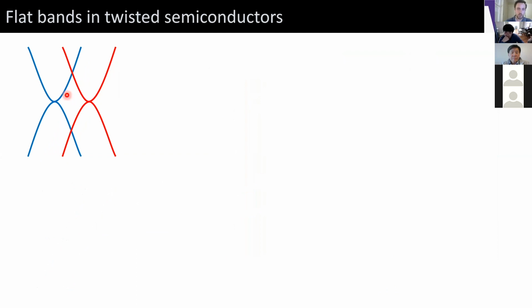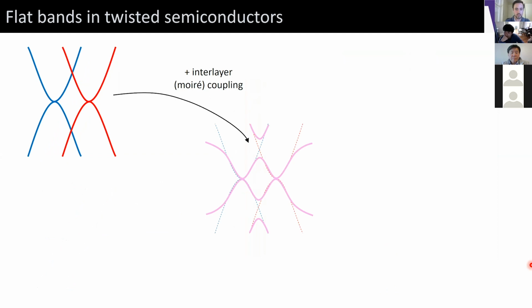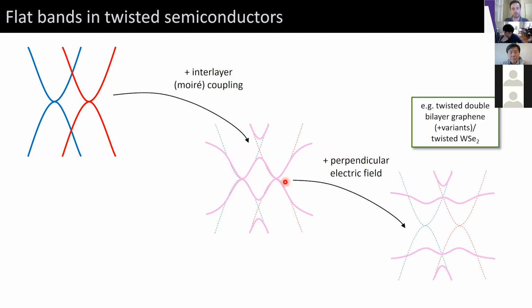If we consider instead just twisting semiconductors, which have more conventional parabolic dispersions, the symmetries of these crystals dictate that not only do we get an energy gap due to low energy Bloch band formation at some finite positive and negative energies, but we're also able to tune the band gap at the neutrality point with a perpendicular electric field. And so now we have control over the width of these bands, not just with twist angle, but also at a fixed twist angle by applying a perpendicular electric field. This is relevant in a number of different twisted van der Waals heterostructures, like twisted double bilayer graphene and similar, which I'll talk about today, and even more disparate systems like twisted WSe2.